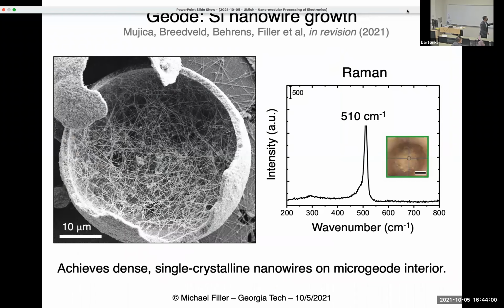And if you grow these in a CVD reactor and you grow nanowires, you get spaghetti-looking things like this. So very high density growth. I show this Raman spectrum, which is basically saying these are silicon wires, because this kind of measurement with a standard Raman spectrometer is not easy to do with usual wire growth techniques. You don't have enough material.